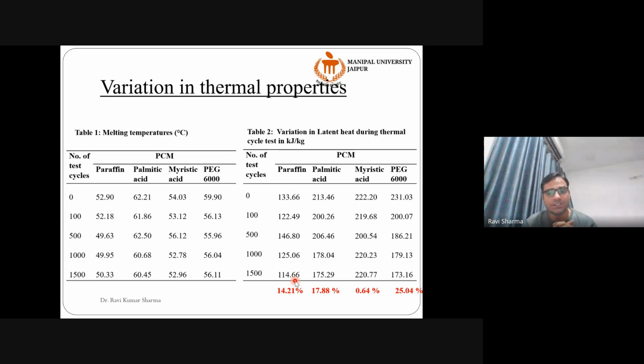Now, as an application engineer, what do you want? You want your material to lose minimum amount of latent heat after a certain number of cycles. And that's what is happening with myristic acid. After 1500 melt-freeze cycles, it loses just 0.64% of its latent heat. So as an application engineer, you can tell your customer that myristic acid is the best material out of these four because it doesn't lose its latent heat capacity over the period of 5 years. And polyethylene glycol is the worst material because it has lost 25% of its total latent heat capacity.